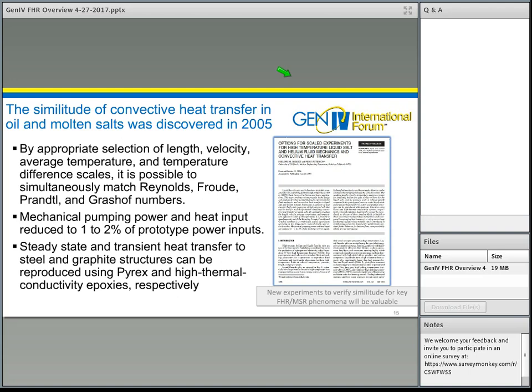Equally interesting, with heat transfer oils, such as Dowtherm, it's possible at reduced temperatures to match Prandtl number, and with the proper selection of the length scales and temperature difference scales and velocity scales, it is possible to also match the Reynolds, Froude, and Grashof numbers, which means that one can simultaneously achieve similitude for both forced and natural circulation flows. With the oils, the scaling gives you actually very large reduction in both the heater power and pumping power that is needed to perform experiments.